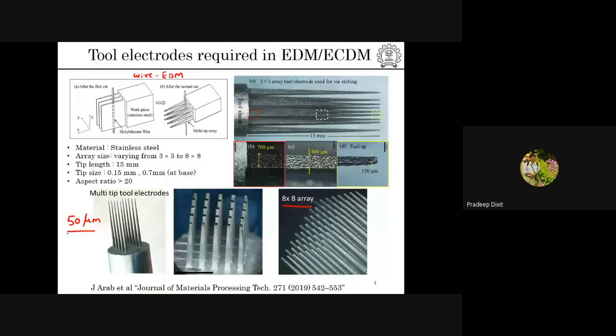Now the question here is that we have learned that for creating smaller holes, the tool electrode size should be in this order. But the fabrication of a tool electrode having such a tip size is very difficult. Using wire EDM, it's not possible. What are the challenges? The challenges come because wire EDM involves a lot of high temperature processes. Naturally, it's an EDM process with a very high temperature, in the order of 2000 degrees Celsius plus.